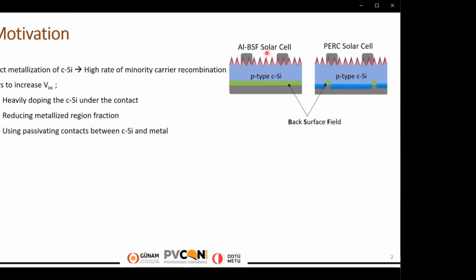In order to improve the open circuit voltage of the solar cells, there are three main ways, which are heavily doping the crystalline silicon under the contact, reducing the metallized region fraction, and using passivating contacts between crystalline silicon and metal. Since the formation of the aluminum silicon region creates recombinative regions, it cannot supply sufficient passivation in the aluminum back surface field case.